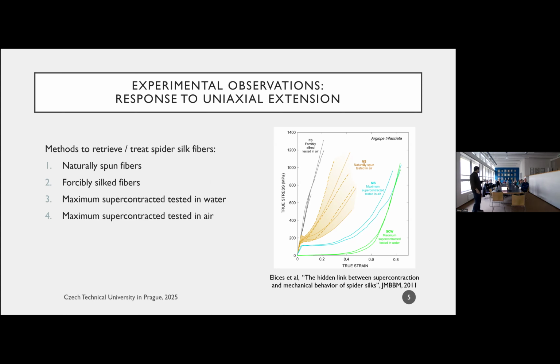That's where people torture the spiders. They take a spider, glue it to some sort of substrate, and then force the silk fiber out of it. It turns out that if you do this, you end up with a fiber with completely different properties. That's the black curve here. This is what we call forcibly silk, and it looks like this.